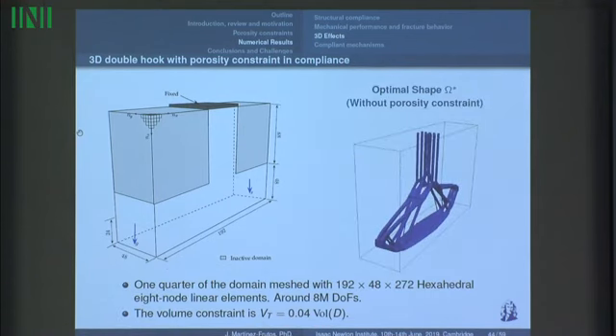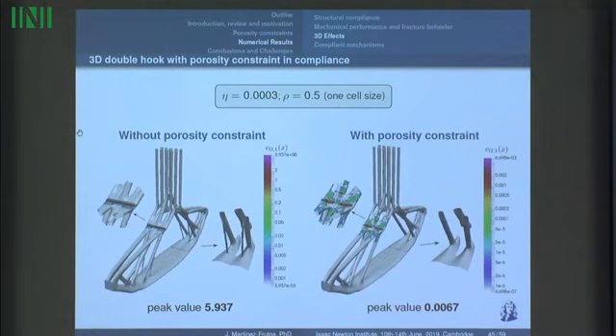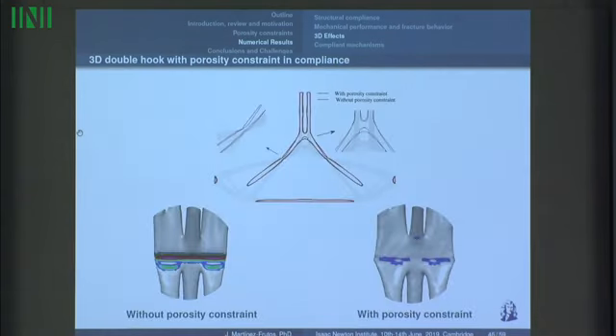And this is the design that we obtain first without imposing the porosity constraint, and taking this design as an initial guess, we have this other design. So if we compare both, the peak value is also reduced 3 orders of magnitude, and we see that what this porosity constraint does is to eliminate thin bars of the structure, and also to round the corner to smooth sharp regions. But there are other effects that, if we zoom here, we can see that in the out of plane direction, the surface of this corner is inflated. So we have also a 3D effect when we solve the problem with these porosity constraints.